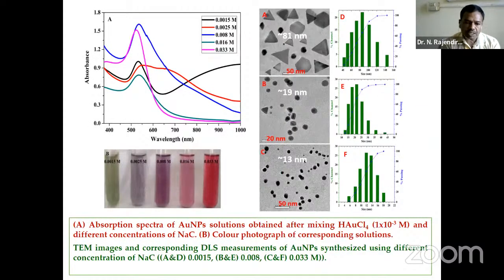So this slide shows the synthesis of gold nanoparticles in different sizes and shapes using sodium cholate as a reducing and stabilizing agent. And here you see from the UV visible spectra that at low concentrations it forms anisotropic nanoparticles, whereas at higher concentrations it forms a spherical nature.